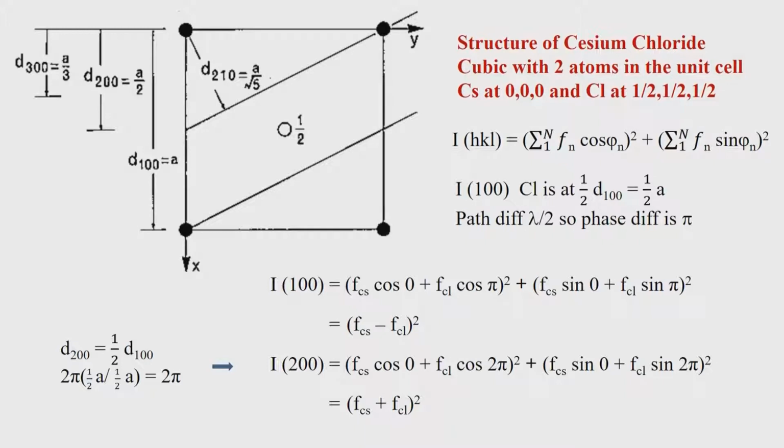That is the one which gives us the ratio of how the position of the atom is with respect to the given plane. For example, if you take 210 here, the chlorine atom is positioned exactly midway between the parallel planes which pass through this point, defining 210, and this is again 210.